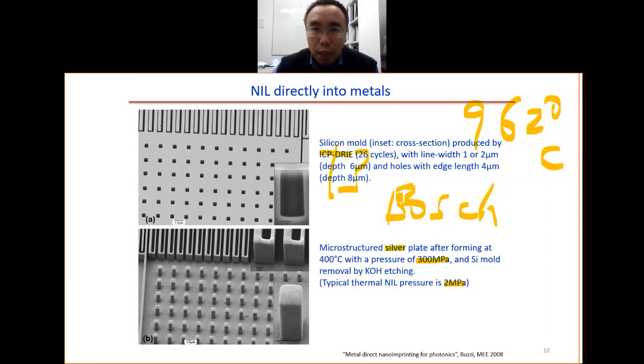Use the Bosch process to make this mold. Because the sidewall is rough and we also have this negative taper angle, the separation will be very difficult. In this case, the mold is not separated from the silver. It is actually dissolved. So the mold is dissolved by the KOH etching. This way you get the silver pattern in the end.